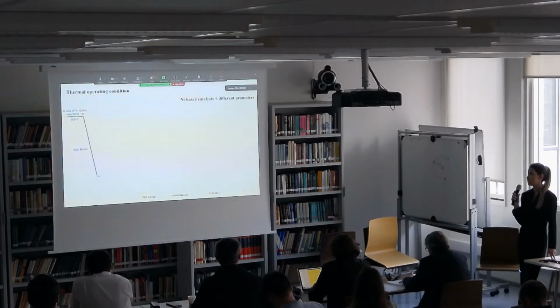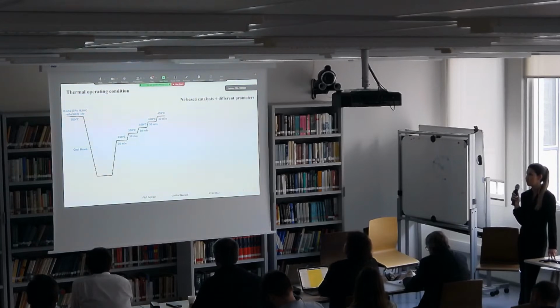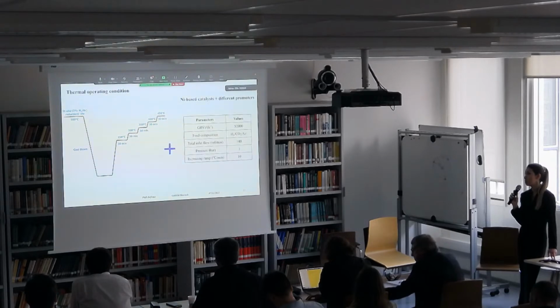So first, the nickel-based catalyst was thermally reduced in situ in a 5% hydrogen argon flow at 500 degrees for 1 hour. Then it was cooled down below 200 degrees. Then with the mentioned condition, the reaction started.